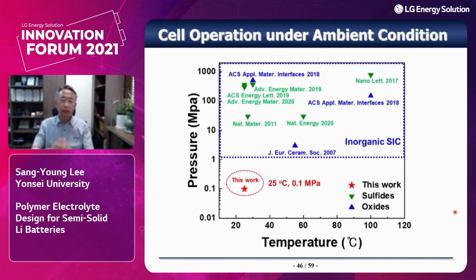Okay, and then here is one significant advantage of our approach. So let me emphasize again. Our cell can be operated under ambient condition like this. We have compared our result with previously reported ones; the sulfide or oxide-based approaches should rely on high pressure or high temperature. By comparison, our printing-based and polymer electrolyte-based semi-solid batteries can operate under mild conditions, which can be practically viable in terms of enabling the commercialization of semi-solid batteries.